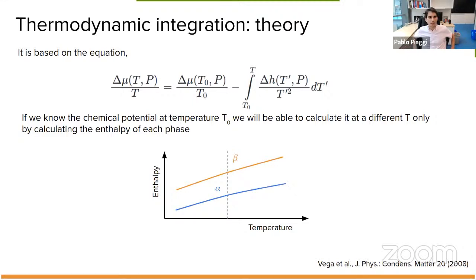And now I'll go to perhaps one of the most common techniques, that is thermodynamic integration. And this is another way to calculate the chemical potentials. Here we have the chemical potential at some reference temperature T0. Provided that we have this, we will be able to compute the chemical potential, or the difference in chemical potential, at a different temperature T just by integrating the difference in enthalpy between the phases. This is, of course, very cheap. The caveat is that we have to know already the solution at a different state point. So we have to know at least that before we're able to use it. But if you do know the difference in chemical potential at some temperature T0, it's a great method.